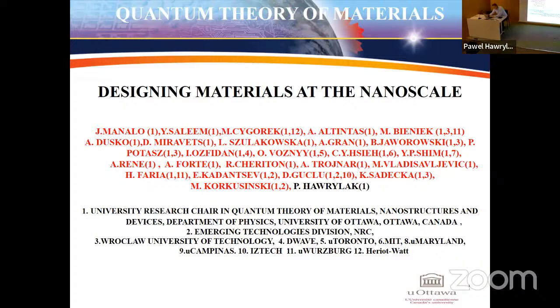With which huge system? For instance, the graphene nanofragment. Yes, the shell is the number of states in the degenerate shell. So there is a whole process, but it boils down to the number of states in a degenerate shell. The one that we studied is of the order of 7 to 10. So you have a degenerate shell with about 10 states. That's something that we have been doing on a Haldane sphere, for example, for a very long time. Okay, so configuration interaction on a limited Hilbert space, limited to the degenerate states. Okay, I see. Thank you. Not all the electrons. No, that we can't. Any other questions?